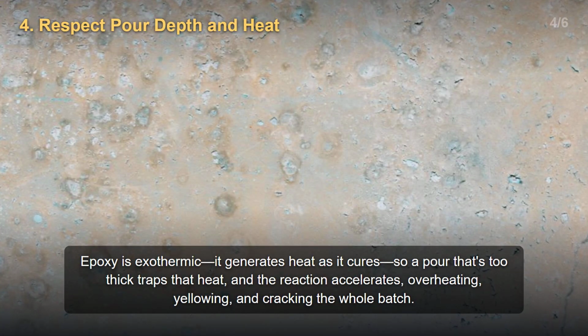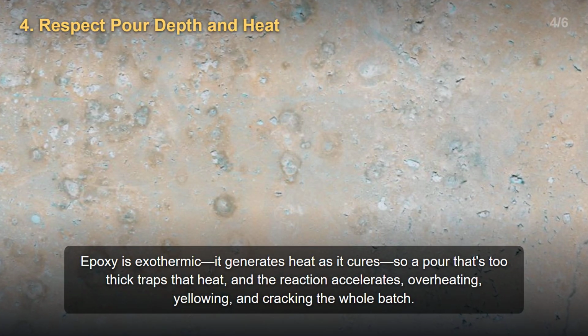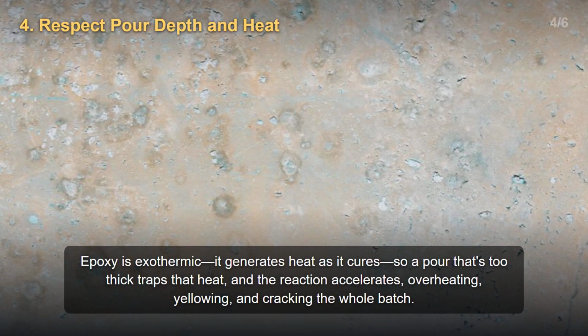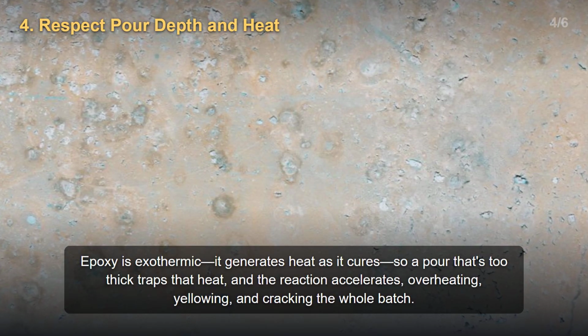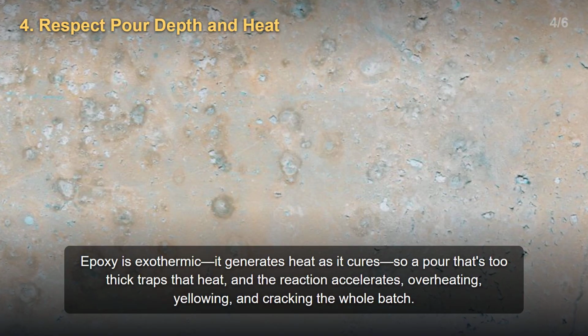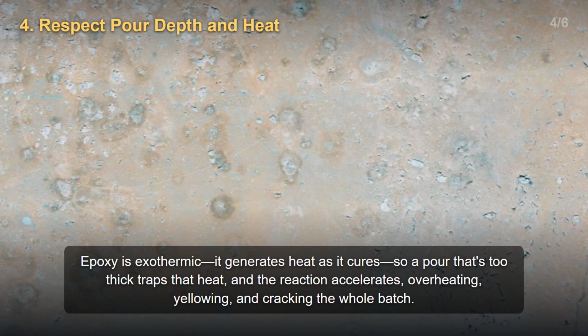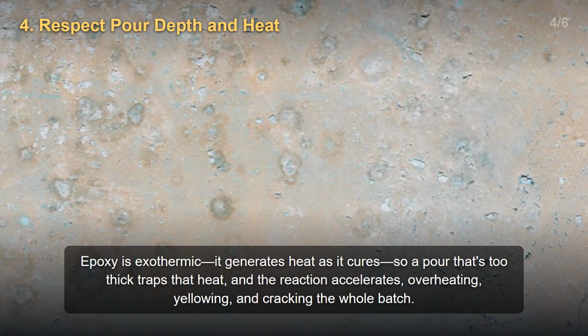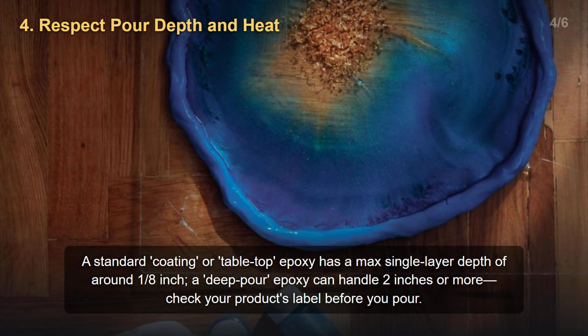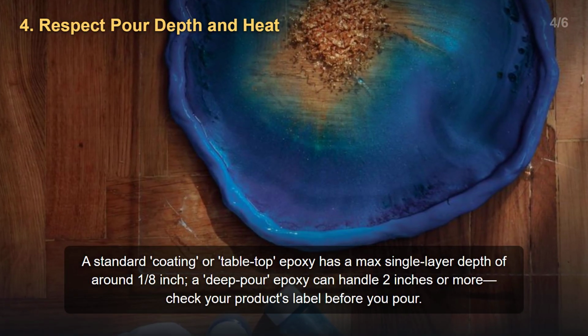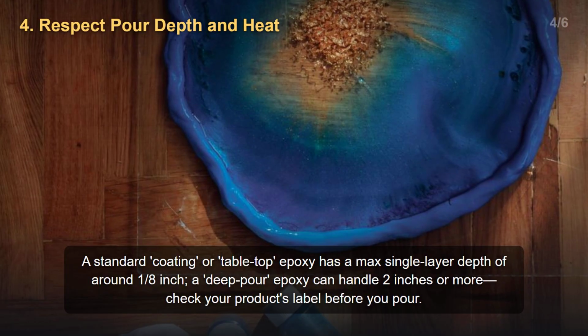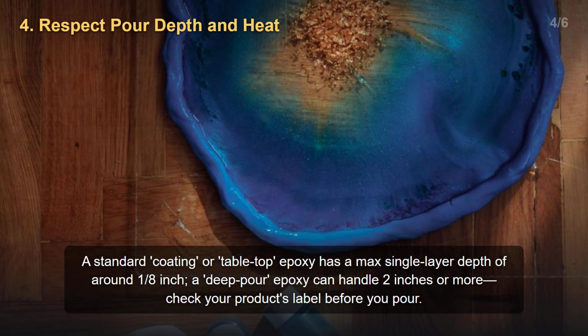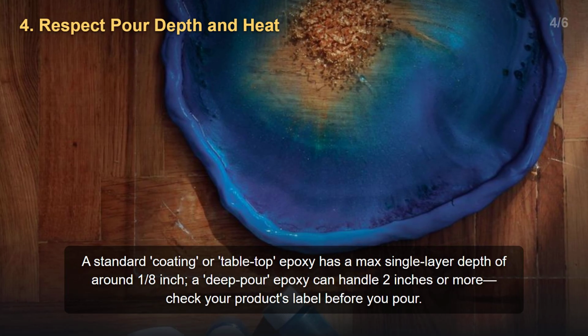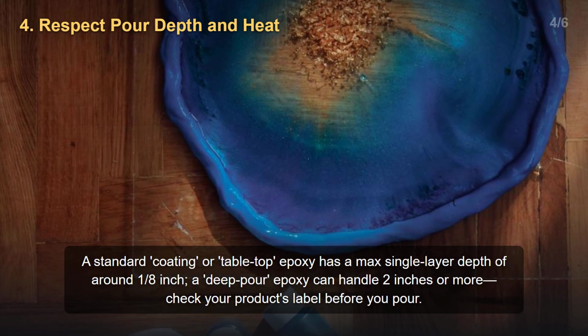Respect pour depth and heat. Epoxy is exothermic. It generates heat as it cures, so a pour that's too thick traps that heat, and the reaction accelerates, overheating, yellowing, and cracking the whole batch. A standard coating or tabletop epoxy has a max single-layer depth of around 1/8 inch. A deep pour epoxy can handle 2 inches or more. Check your product's label before you pour.